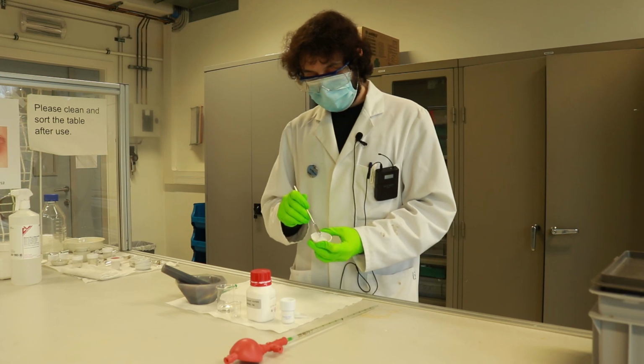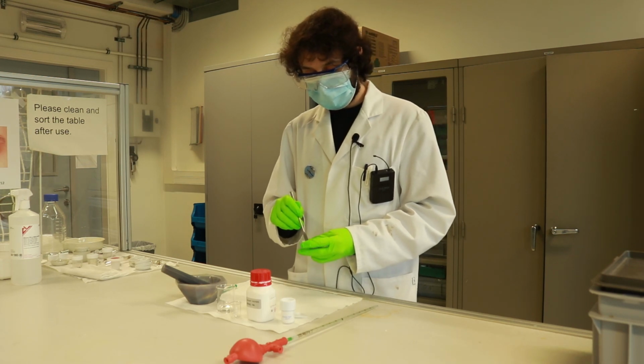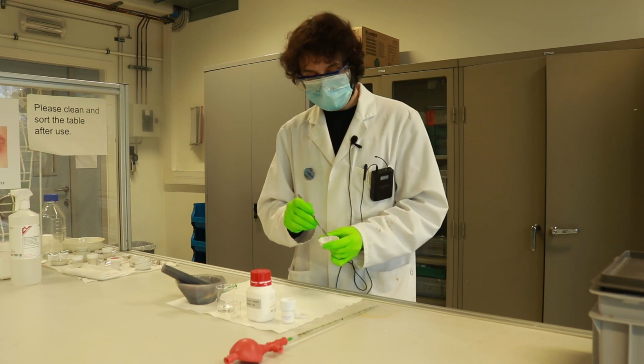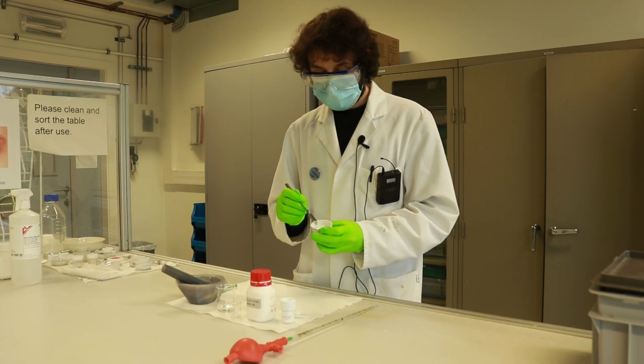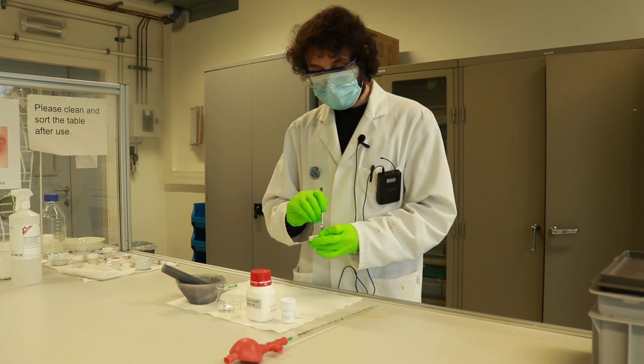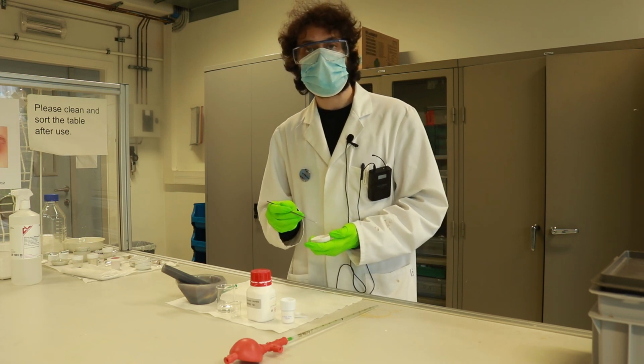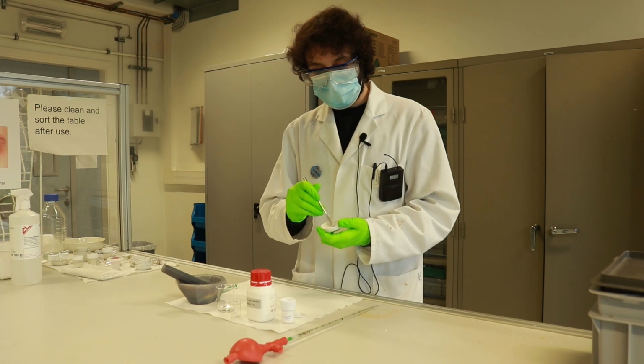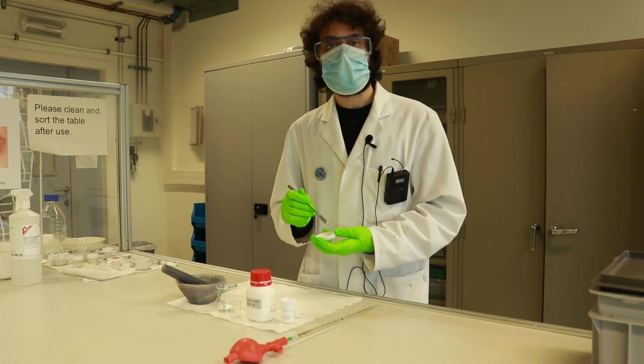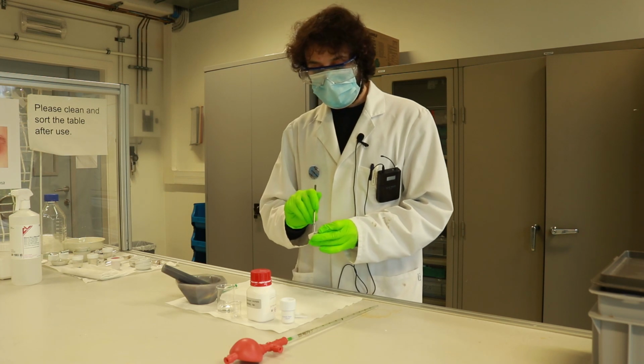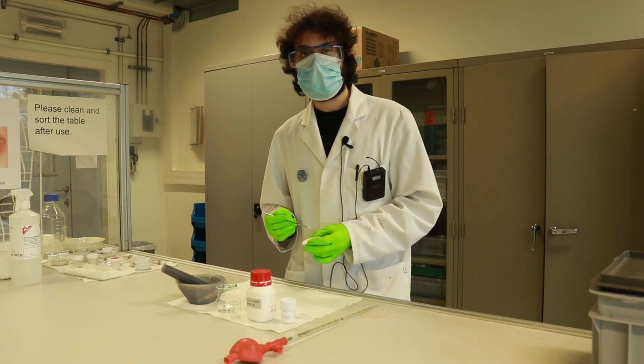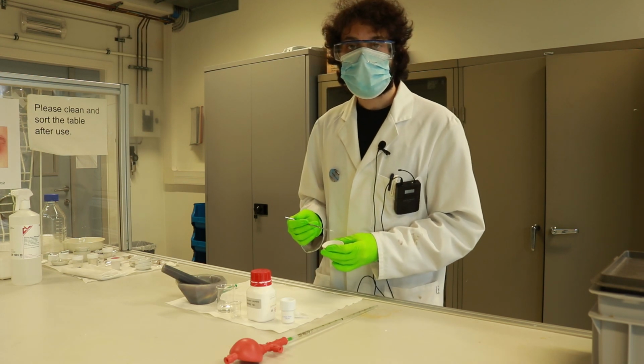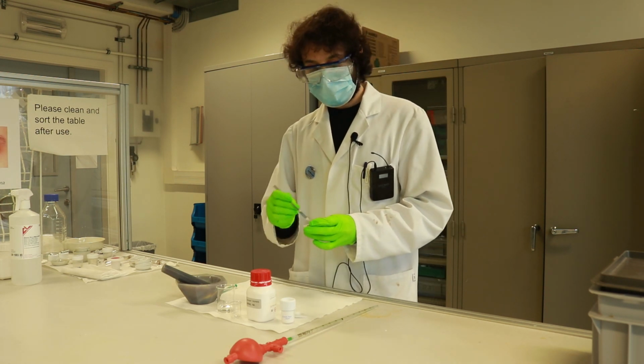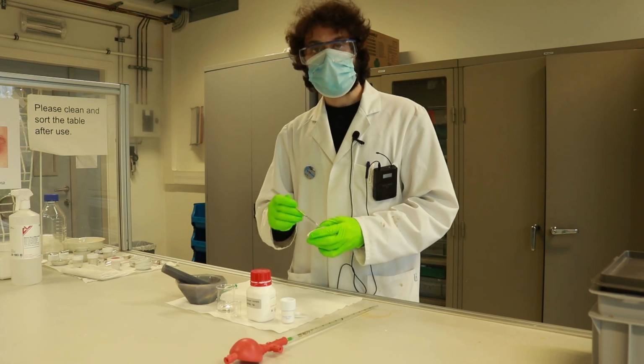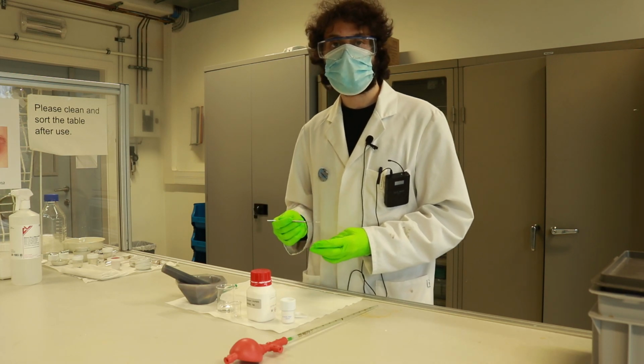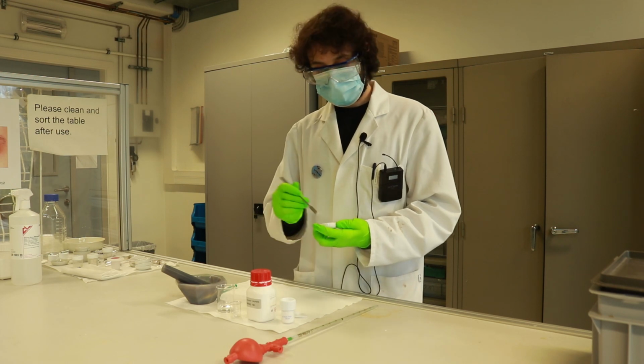Now that we have our nickel nitrate dissolved, filling up the pores of our support, it's time to dry the sample. Usually samples are dried anywhere between 80 and 120 degrees, and that's just to remove the very last remaining amounts of water. After that, we perform a calcination step at a slightly higher temperature to remove and decompose the nitrate so that we are left with nickel oxide only on the support.